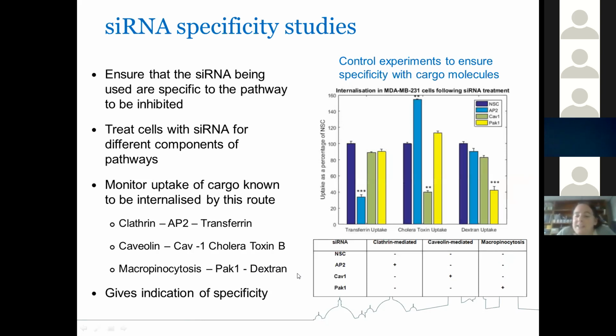And in all cases, we could see that when we had knocked out the relevant protein, the amount of uptake decreased. So when we knock out AP2, we can see that the amount of uptake of transferrin is reduced. When we knock out Pak1, we saw that the uptake of dextran was reduced compared to the other proteins. So the knockdown worked well.